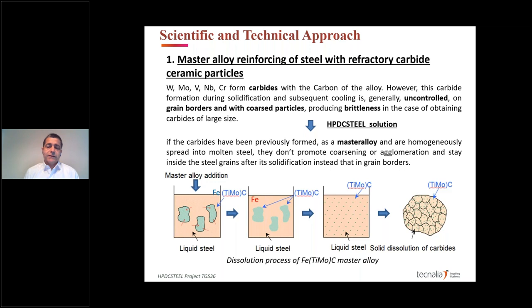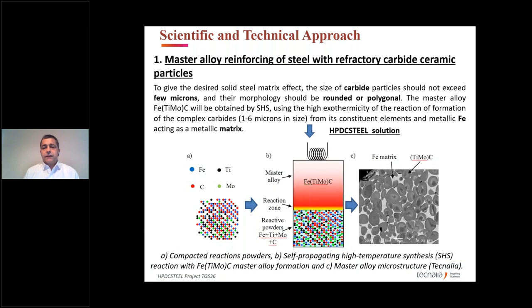We have made many trials and many projects over the years, and one of the key points is how to produce this master alloy. So we have been working with the self-propagating high temperature synthesis process, the SHS process, where we make a mixture of different powders that can be pure metals, or for example ferro alloys. After, with these powders, we compact and, with an electric discharge, we make a self-propagating reaction where we obtain a matrix that, in this case, is the iron, with round ceramics that are the ceramics that we want to add to our alloy.